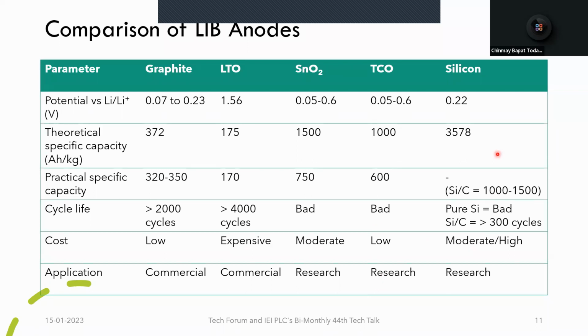Silicon, on the other hand, has been a popular choice in the past 10 or 15 years to succeed graphite or combine with graphite to give us longer range EVs due to its extremely high specific capacity of 3578 ampere hour per kg, which is 10 times that of graphite. Silicon alone has a lower conductivity and poor structural stability as compared to graphite. Therefore, at the moment, silicon is being combined with some sort of carbon in the form of graphite or other forms of carbon, so that we form silicon carbon composites, which can have a capacity of around 1000 to 1500 ampere hour per kg and more than 300 cycles. And they are still in the research stage.